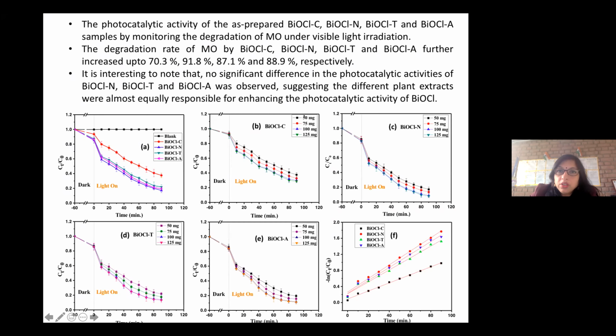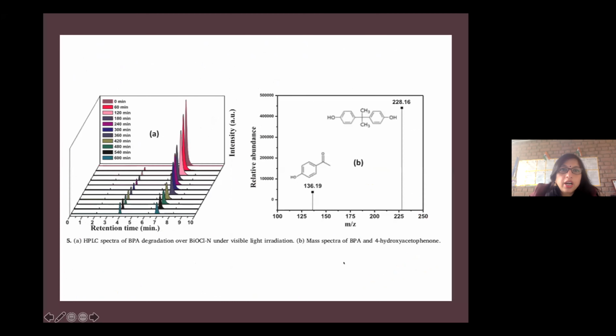So here for the chemical one, to optimize the dose, we found that 100 mg is the optimized dose in both cases, in this case and this case. So this N is representing the green one, C is the hydrolysis only, and T and A is also showing 100 mg as the optimized limit. Then reaction kinetics showed that this follows the pseudo first order kinetic model. And then HPLC and mass spectra showed that bisphenol A was degraded by this BiOCl into 4-hydroxyacetophenone. So it is very, very much less harmful compared with bisphenol A.